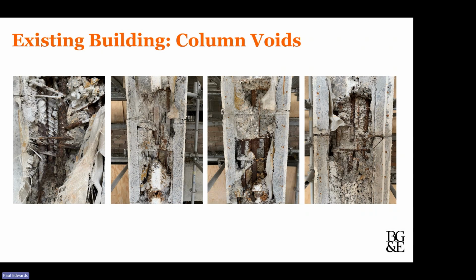So this was discovered by undertaking a small drill into the precast concrete and then finding that there were voids. And then once the voids were found, it was decided to saw cut off the one face of the precast concrete to understand the nature inside. And you see what you can see here. There's obviously been issues in pouring and compacting well the concrete, leading to significant voids in the precast column molds, which is obviously not desirable. And this was simply rectified using, in effect, a concrete replacement for the new columns and then covering them up.